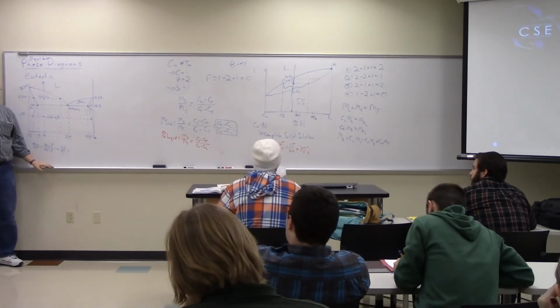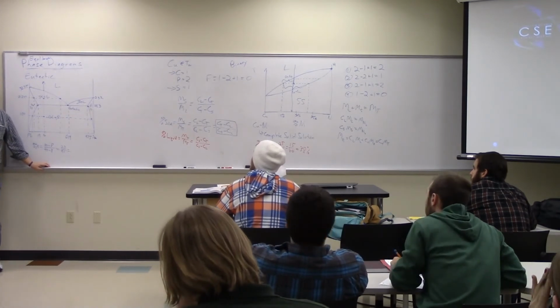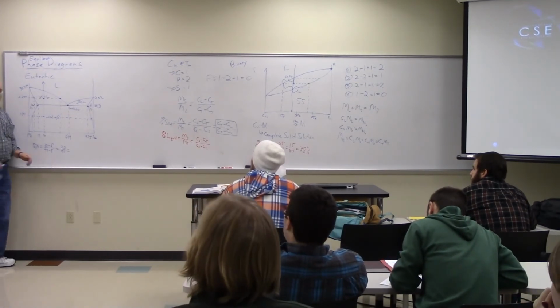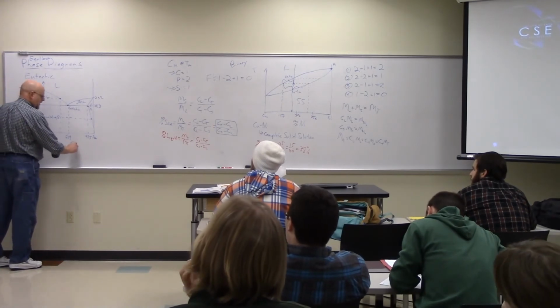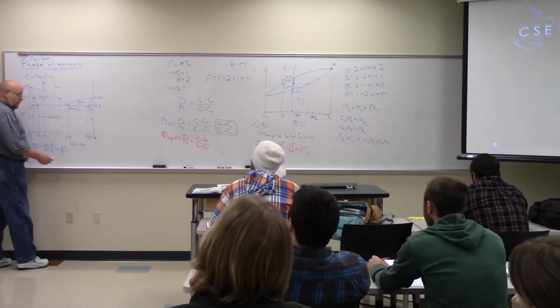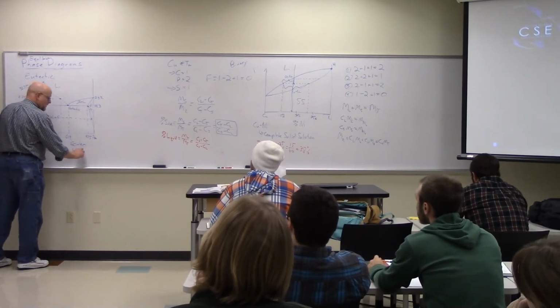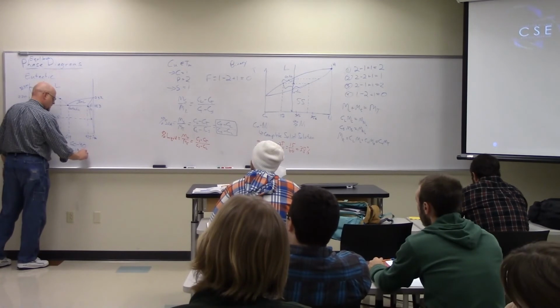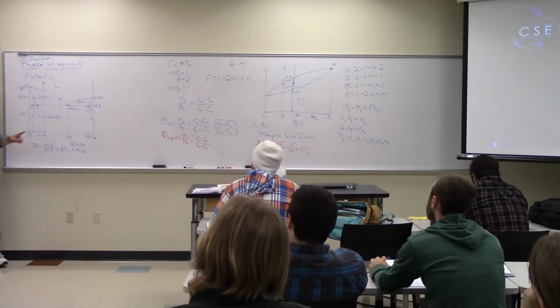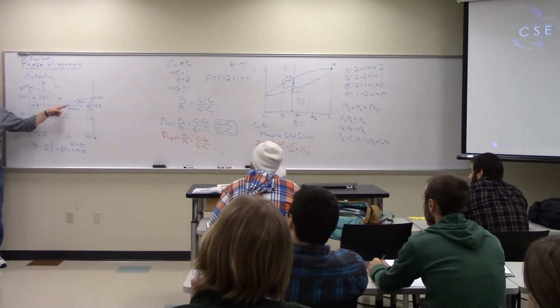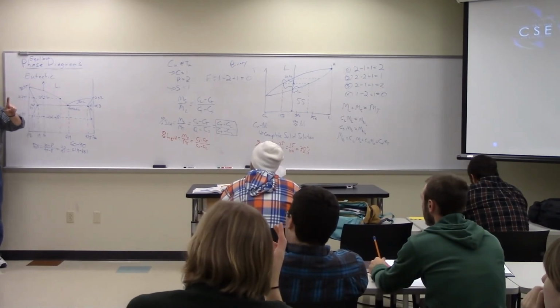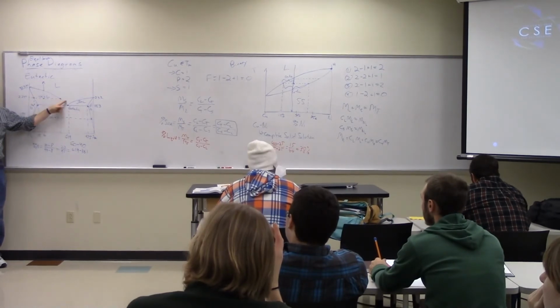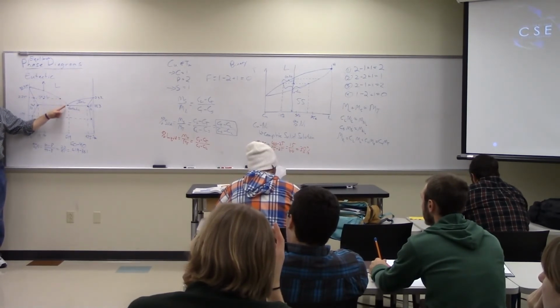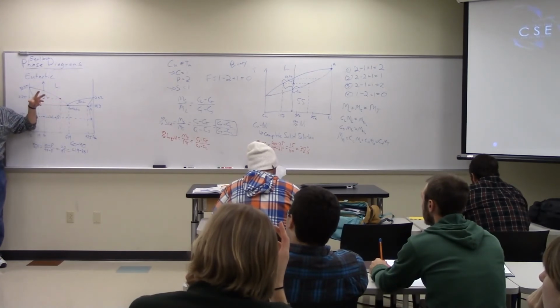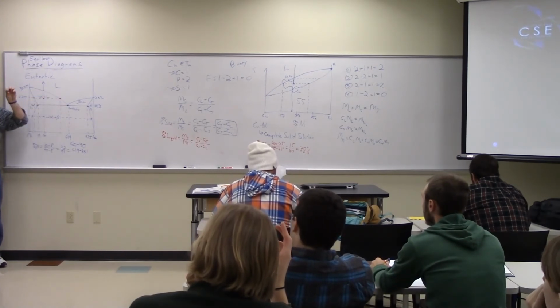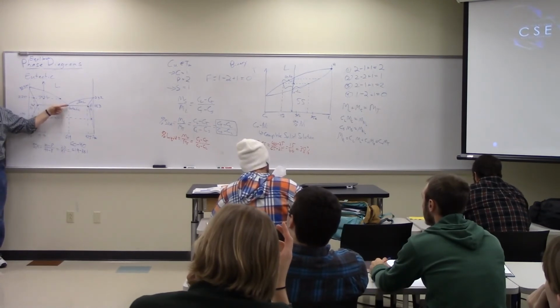So is that like what happens when solder dries? It just kind of instantly dries? Right, and that's why lead tin solder, if you ever look, is labeled as 60-40 solder, or sometimes even 61.9, 38.1, because we're shooting for that temperature, that composition. Because you want a single temperature at which it goes from liquid to solid. If we had truly 60-40, we'd come down here, and it would start to turn into a slush before it solidified, because little bits of it would solidify as the liquid continued to cool.